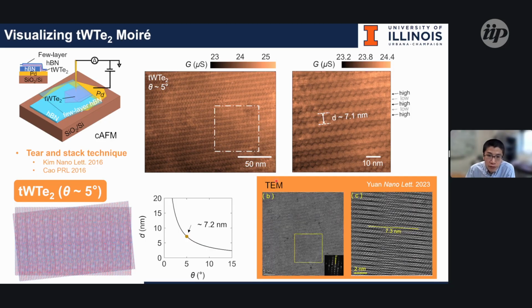Moreover, we confirm this with a TEM study. You can see that with a 5-degree twisting, the system shows around 7.3 nanometers in spacing. This consistently shows that the Moire structure can give you very nicely well-packed cozy 1D structures.